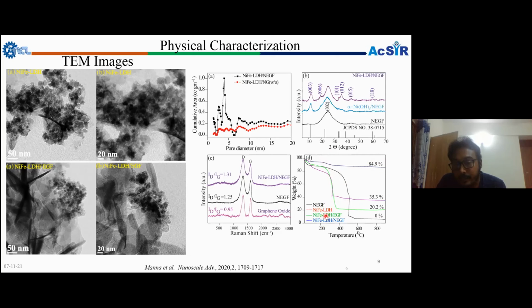But the other two are the nickel iron layer double hydroxide entangled graphene framework and the nitrogen doped entangled graphene framework. So these two suggest the importance of nitrogen for metal nanoparticle loading over the carbon substrate. Here you can see, in absence of nitrogen doping over the carbon, metal loading is less compared to in presence of the nitrogen. So it changes from 20% to 35.3% in presence of nitrogen. Already in the TEM images we showed that a uniform distribution and more numbers of metal layer double hydroxide can anchor over the nitrogen doped entangled graphene. But in absence of nitrogen there is less, and in the TEM image also there is agglomeration of the particles and fewer particles supported over the graphene. So from that we confirm the importance of nitrogen doping over the 3D graphene and how the nickel iron layer double hydroxide is distributed.